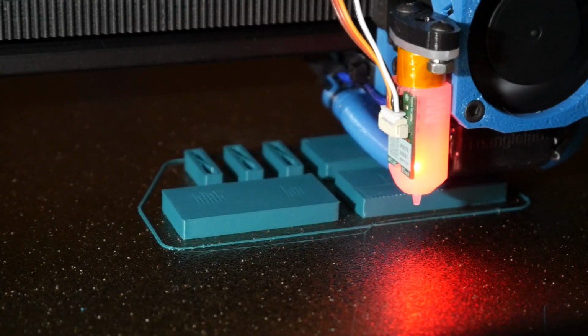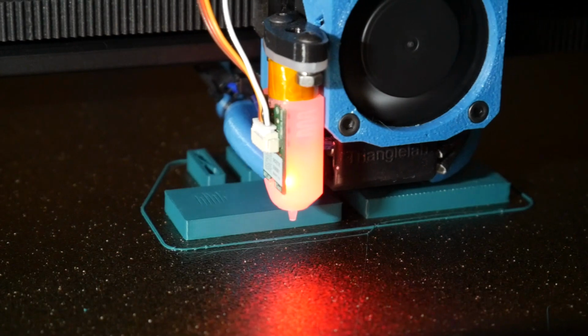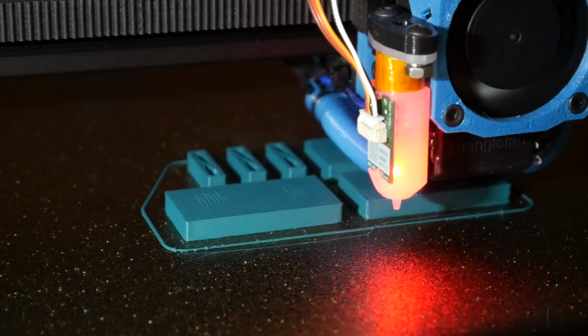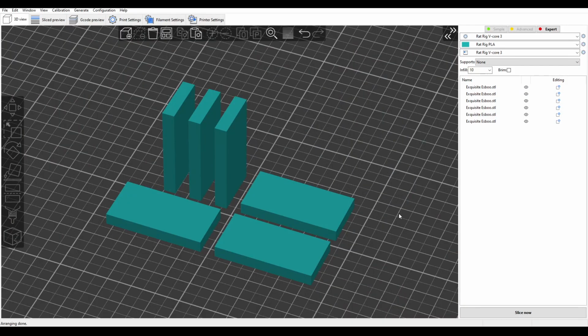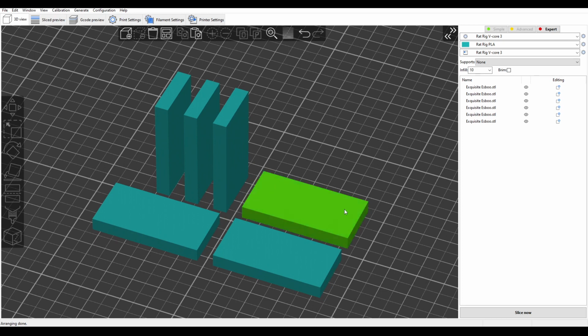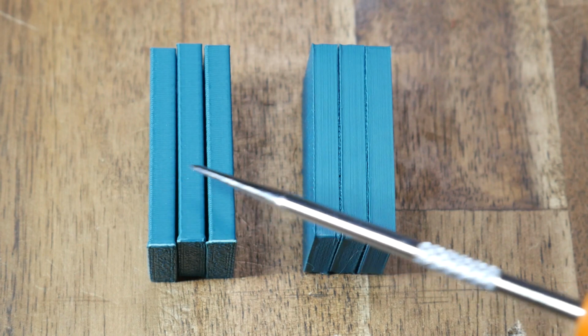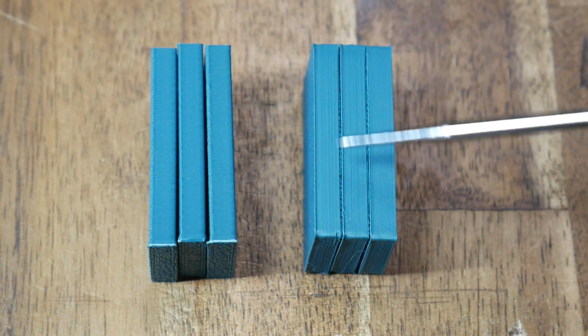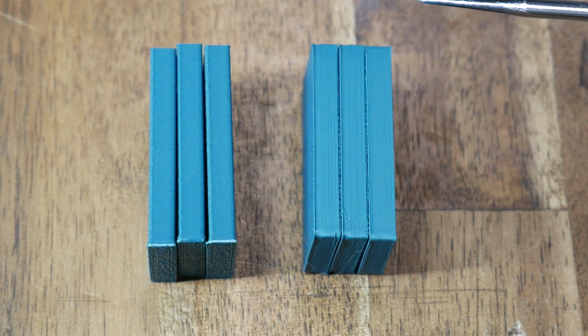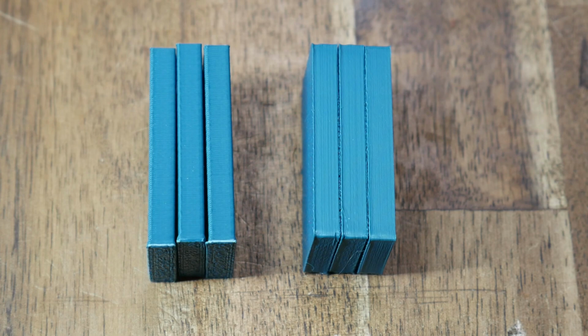To match this with FDM 3D printing, I took this simple rectangular prism and printed a series of them, with half of them laying down flat and the other half standing on their smallest side, oriented vertically. Much like the timber, that gives us a sample set on the left, where the layer lines go horizontally, and a sample group on the right, where they're extending vertically.